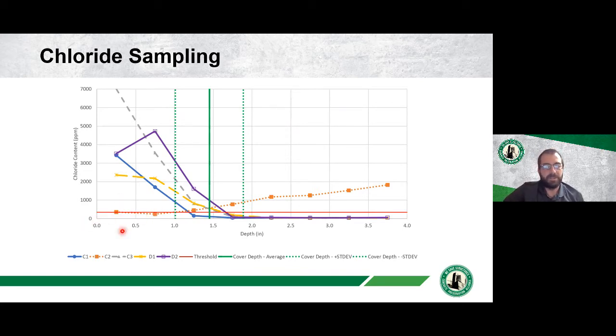So at 350 parts per million, the risk for corrosion is high. So if the chloride concentration at the steel depth range is above this red line, then the risk for corrosion is high. And we can see here we have a high surface concentration and then it decreases with depth. And we can see that for several of these lines, if we're 1.5 inches or shallower, the risk for corrosion is quite high. The chlorides are well above the 350 value.